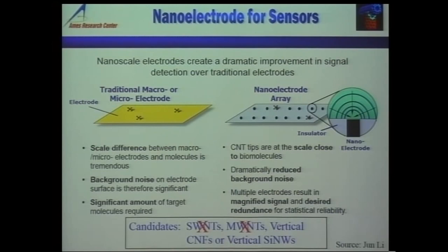On the other hand, if you take the same micro electrode and divide it into many different nano electrodes, the size difference between your molecule and the electrode goes down, and you significantly enhance the signal-to-noise ratio. There are also multiplexing opportunities. What material can you use? Single-wall carbon nanotubes look like spaghetti on a plate in SEM images — it's very hard to have controlled electrochemistry on them, controlling size and putting functionalities on them. Even multi-wall nanotubes grow like towers right next to each other.